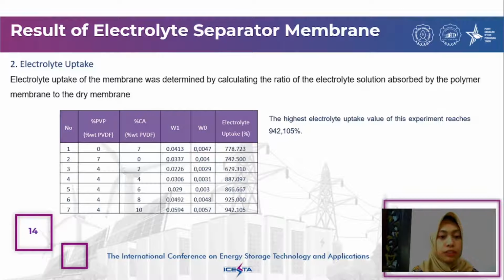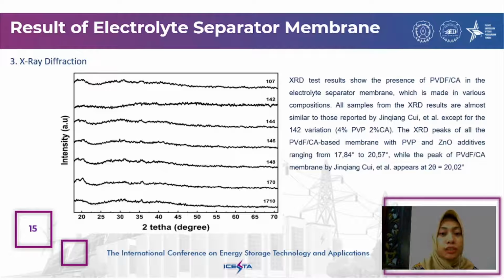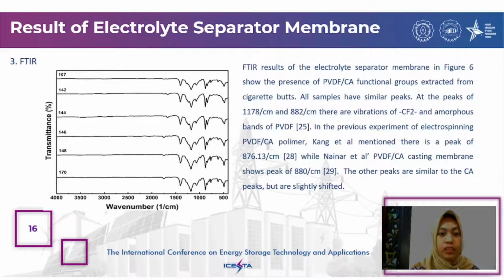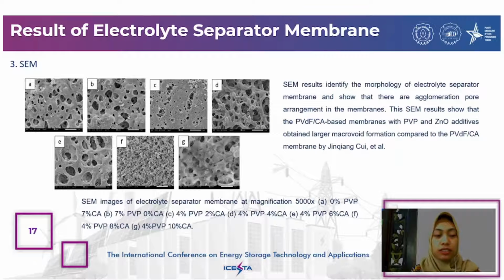The electrolyte uptake of the membrane was determined by calculating the ratio of electrolyte solution absorbed by the polymer membrane to the dry membrane. The highest electrolyte uptake value of the experiment reaches 942.105%. This is the result of electrolyte membrane separator XRD. The result shows that there are PVDF and CA in the electrolyte membrane separator, which is made in various compositions. And the FTIR result of the electrolyte membrane separator shows the presence of PVDF and CA functional groups extracted from cigarette butts too. This is the SEM result of the separator membrane, and this identifies the morphology of the electrolyte separator membrane and shows that there is agglomeration and pore arrangement in the membranes.